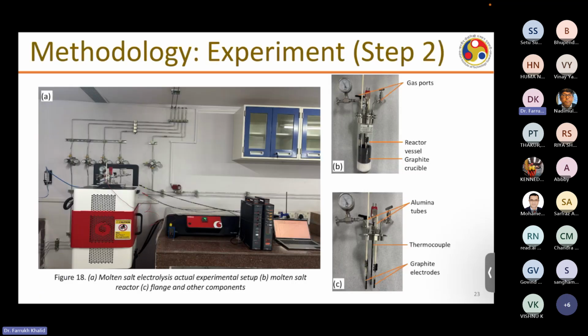So this is again the experimental setup that we used for the electrolysis process. As I mentioned, the challenge was the molten salt, which is highly reactive to any kind of metal or metal-based alloy. Whether you use stainless steel or another, it will be highly corrosive. So in order to avoid that, we used an alumina tube. The reactor and other fittings are made of stainless steel, and then we use graphite electrodes, and alumina tubes were also used.